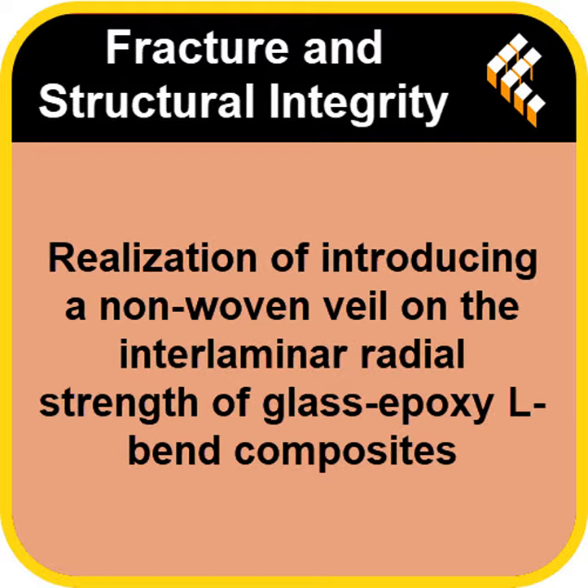And how did they test the strength of these L-shaped samples? You mentioned making sure the failure starts in the right place. Yes, that was critical. To really isolate the effect of the veil on stopping delamination, you need the crack to start consistently. You don't want it starting randomly somewhere else. So they needed to pre-damage it slightly. In a very controlled way, yes. They embedded a very thin copper wire, just 0.2 millimeters thick, right at the middle layer interface. Okay. Smack bang in the center of the curved part between the 8th and 9th layers. This little wire acts as a crack initiator. A guaranteed starting point for failure.